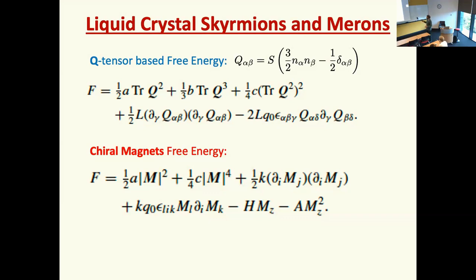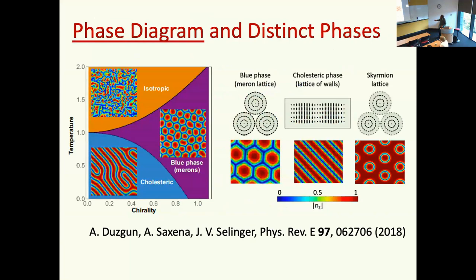And that Q tensor is defined in terms of the components of the director field like this, and S is some scalar order parameter. Now, just like in magnetism, you have some free energy, double well here, you can have trace of Q; so this is the free energy in terms of the Q tensor for the liquid crystal. Here you have magnetic domain walls and chirality, because I talked about the Dzyaloshinskii-Moriya interaction, that means there was chirality, and Zeeman field and anisotropy. Here, these two terms are elastic interaction in liquid crystal. This is just like the gradient squared. This tells you that if you do bending, splay, or twist, it costs you some energy. Here you have a minus sign and q0. q0 is some inverse length scale. This tells you that the system will prefer chiral nematic order. Okay, so this is elastic. You can do the analysis, but I'm not going to go into this given my lack of time. And you could create a chirality versus temperature phase diagram.